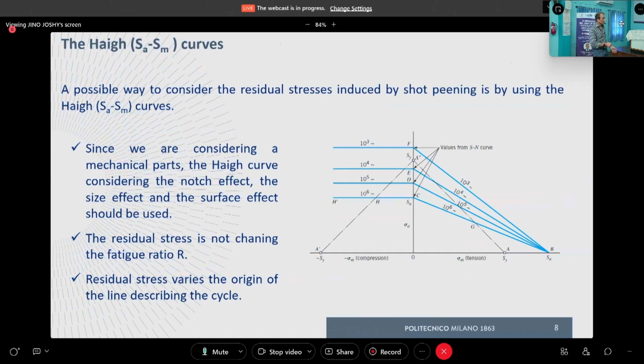How can we consider the residual stresses with this approach? The residual stress acts as a sort of initial point, initial condition. Without shot peening, and if we neglect the presence of residual stresses, each fatigue cycle starts from this point, and imagine that this can go at 45 degrees, the pulsating fatigue. This will be the limit. If we are considering the application of shot peening and the consequent residual stresses, the initial point moves here. The cycle remains the same, inclined 45 degrees, and here will be the limit point. And we can see that indeed the length of the segment that defines the possible amplitude of the fatigue limit is much larger considering compressive residual stresses.